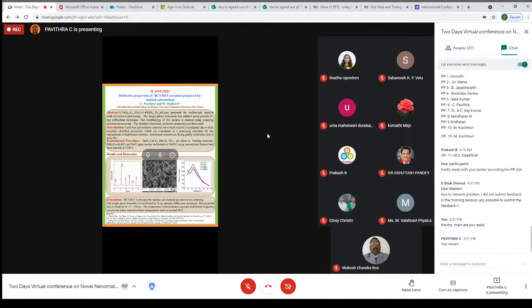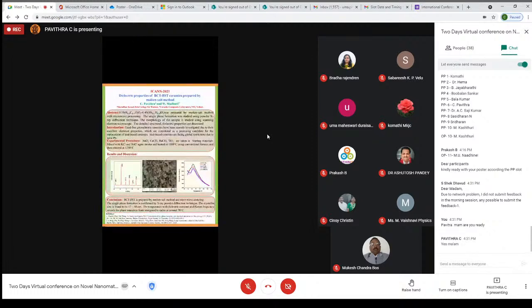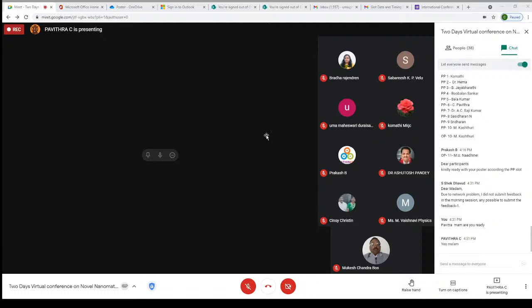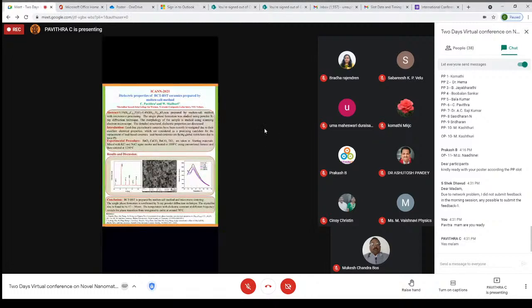In this, I have chosen a lead-free material. Lead-free material is good for the environment, and at the same time it shows a very high dielectric constant. That is why I have chosen BCT, barium calcium titanate, and BST, barium strontium titanate, prepared by the molten salt method. Molten salt is a very easy method to prepare a sample. We take the starting materials as raw material and mix them with NaCl and KCl salt, directly mix in an agate mortar and heat at 1000 degrees centigrade in a conventional furnace.